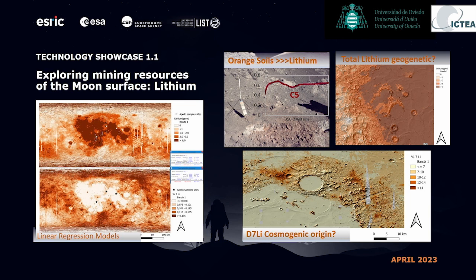With this data, we carried out two linear regression models, one for the total concentration of lithium and the other for the lithium-7 isotope. We extended this model using the raster calculator of QGIS and the Clementine imaging and obtained two maps, these two maps. But for me, the most important results of this research are related to the distribution of the lithium-7 isotope. One important result was the importance of the orange and glassy soils variable in the linear model of the lithium-7 isotope.